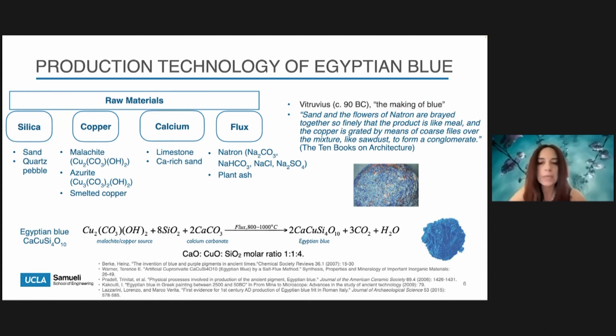Based on the data obtained from such previous studies, possible raw materials include beach sand or quartz pebbles, malachite, azurite, or smelted copper, limestone or calcium-rich sands, and natron as the flux to lower the melting temperature of silica. Also, we know from reverse engineering and experimentation that in order to sinter it into a dark blue solid, these raw materials must have a molar ratio of calcium oxide, copper oxide to silica of 1:1:4 and fired between 800 and 1000 degrees Celsius at oxidizing conditions.